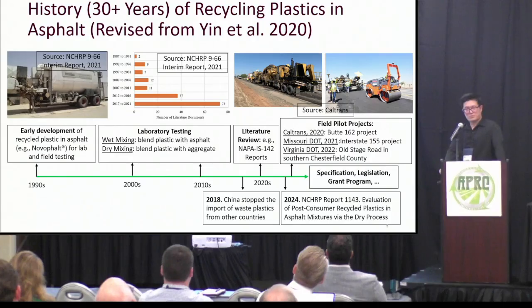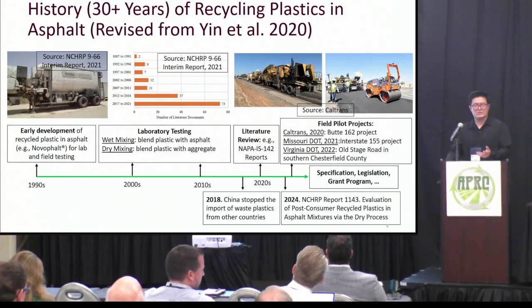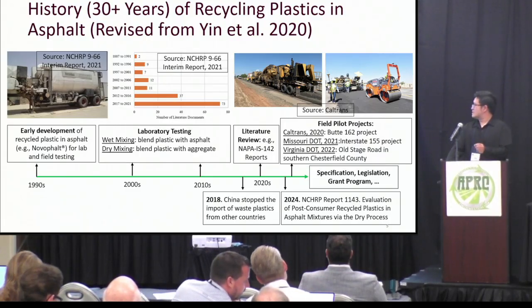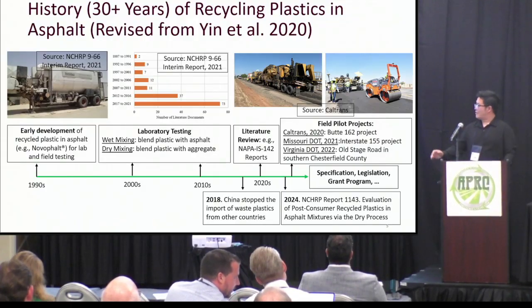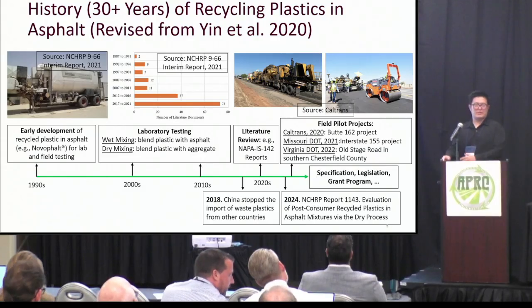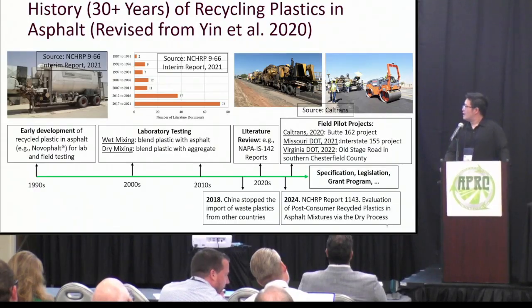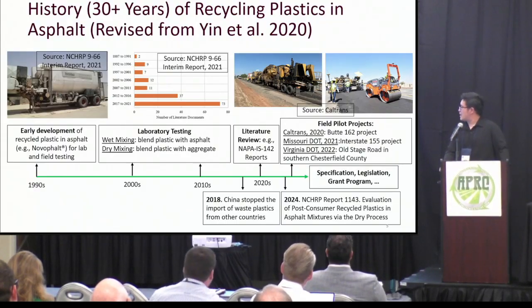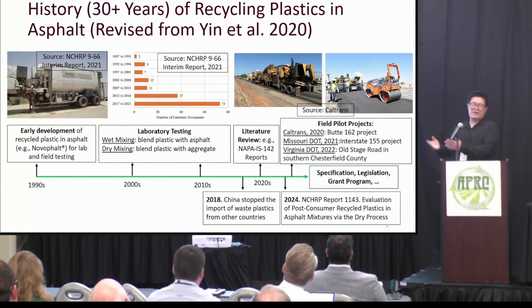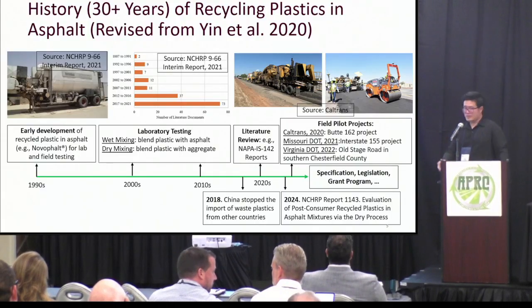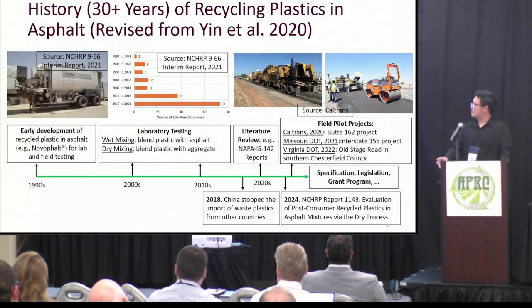So generally, we have two methods to incorporate the plastic in asphalt pavement. One is called the wet mixing method, which blends plastic with hot asphalt first. So the plastic is an asphalt modifier, and then we add the modified asphalt into the aggregate. And one is called the dry mixing method. So we blend plastic with aggregate first, and then we add the unmodified asphalt. So in our project, we evaluate both methods to incorporate the plastic into asphalt.